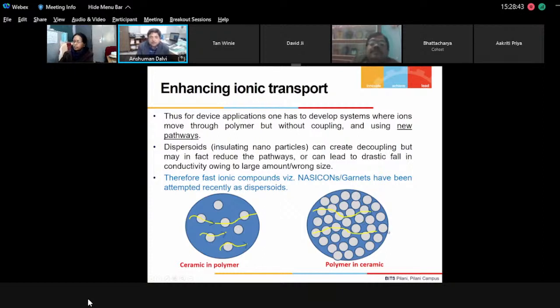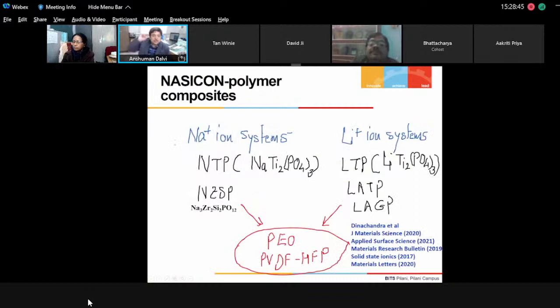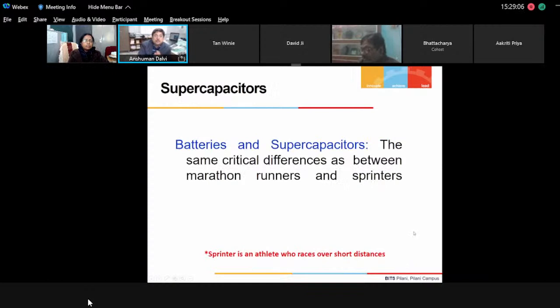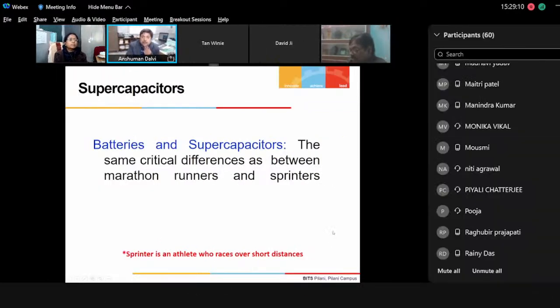becomes quite smooth. So we did a lot of work on these materials in sodium and lithium structured NASICONs, and tried to understand the mechanism of electrical transport, tried to enhance the conductivity, and also obtained a conductivity between 10 to the -3 and -4 in the solid state, in the solid polymer state. And therefore we thought that now it's time to apply them somewhere and see how interesting results one can obtain.